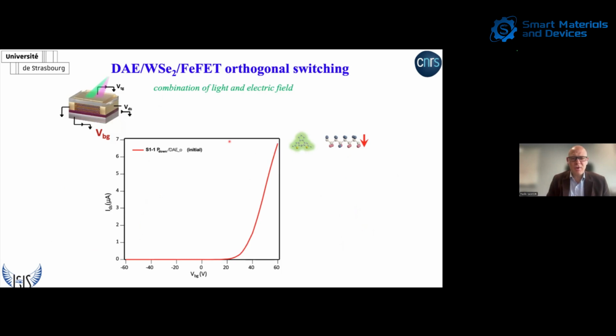Now, let me also show you how you can use the two stimuli independently, but on the same device together. So, with a device in which all the dipoles are pointing down and the diarylethene are in the open state. So this is the highest current that we can observe in our device. Then what happens, we illuminate with UV light, we close the diarylethene, we create optically some traps, and we lower the current through the junction. Still, all the dipoles are pointing down. Then we apply minus 60 volt, we swap the dipole orientation, which now are pointing out of the surface. This is the lowest current that we can achieve.